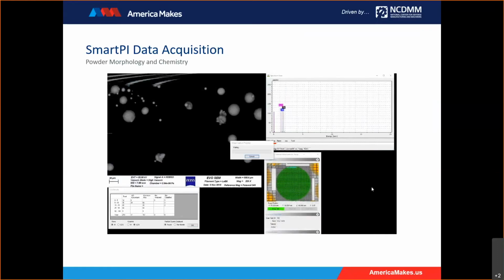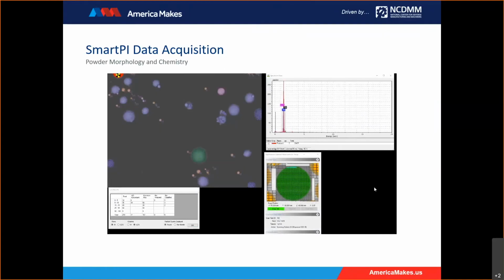The particles are segmented from the background and classified according to size or chemistry. What's nice is that we can monitor the stub acquisition process by looking at the green schematic of the stub in the acquisition status window. Now that we've acquired a few tiles, a few squares at the top are light green. Below the schematic in SmartPI, it will tell us how many tiles we've acquired, how many there are to go, and even the percentage of the target number of particles that we've chosen to acquire.